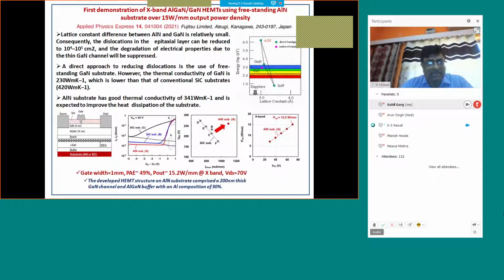Although the substrate size developed so far is only 2 inch, a lot of research is going on, and in the near future we may see devices based on aluminum nitride substrate because of better grown layers with minimum defects. Normally on silicon carbide, the dislocation densities are of the order of 10 to the power 9 to 10 to the power 8 per centimeter square, which are basically defects, and that is mainly because of the lattice mismatch of 3 to 4%, whereas here the lattice mismatch is very, very less. So the defect density reported is of the order of 10 to the power 4 to 5, which is very good. So these devices have very high potential, and maybe in future